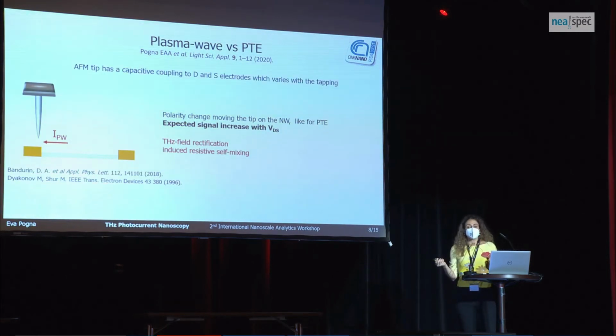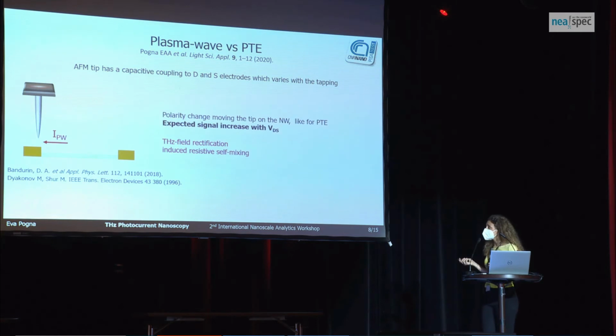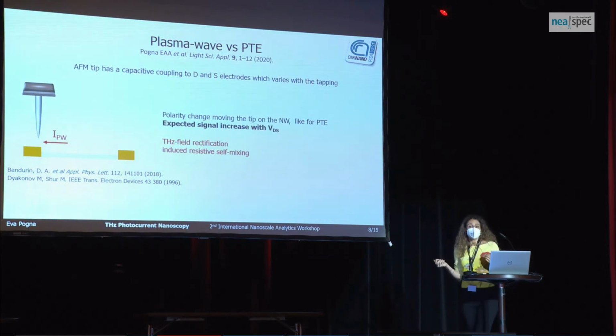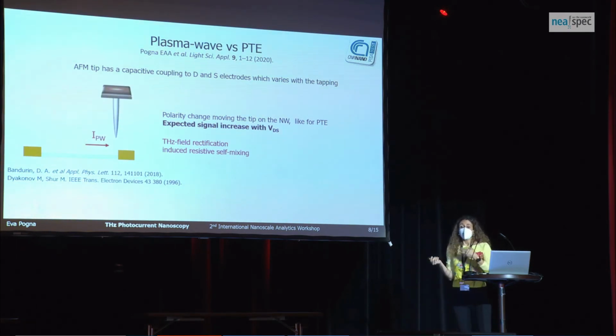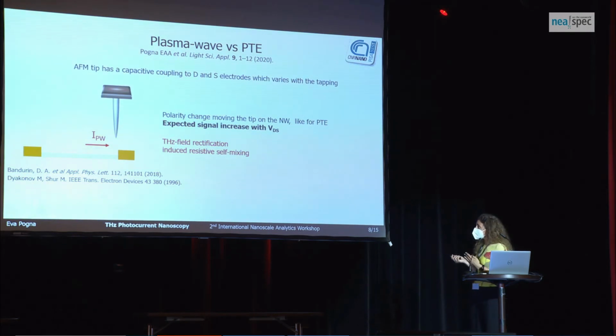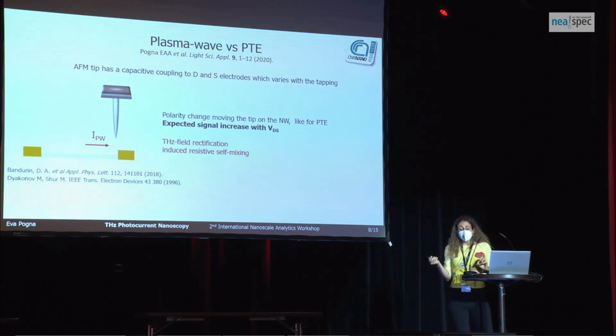We mention another possible effect, which is the plasma wave excitation, which can in principle be detected by near-field photocurrent nanoscopy, because there is a capacitive coupling between the AFM tip and the electrodes. So as the tip moves across the nanowire, we can see a photovoltage which arises from this coupling. And we expect to see a line profile similar to the photothermoelectric effect, so with a change in polarity as the tip scans the sample.